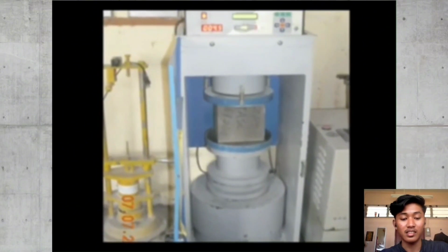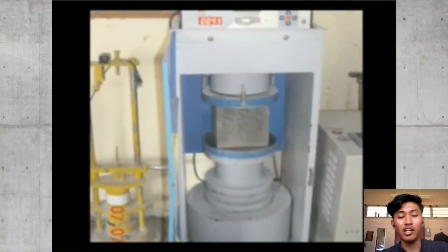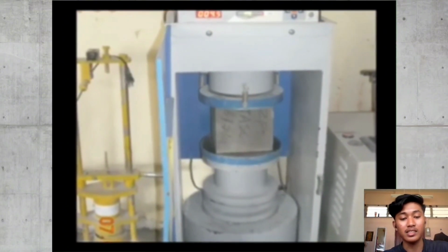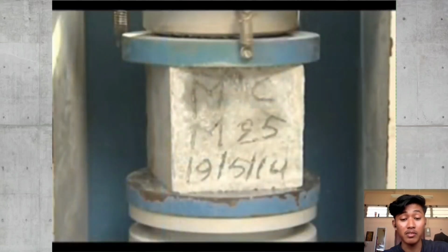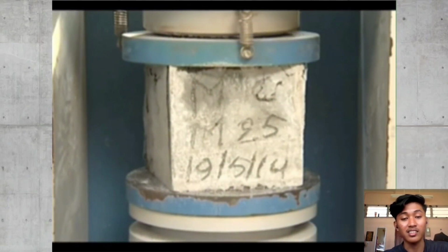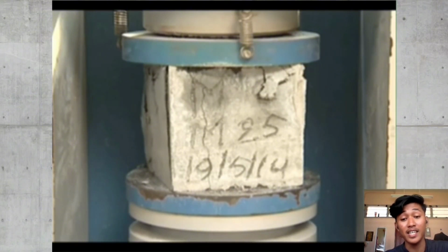In this study, a total of 6 SCC cubes with a dimensional size of 150 by 150 mm have been cast and cured for 28 days. After 28 days of casting, the concrete cubes are tested on a compression machine, assessing the quality of concrete and compressive strength after testing at 7 and 28 days.